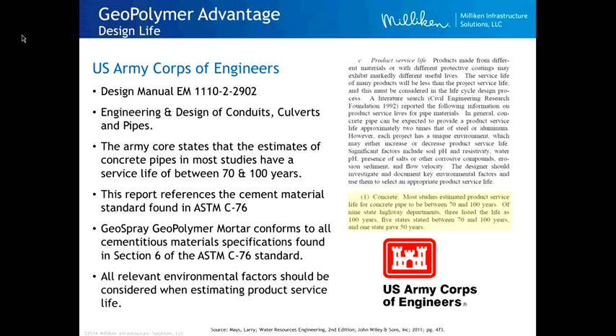And so with that material, the Corps back in the 90s did some studies on different culvert materials, and what they did is they reviewed durability studies that were out there. I know Ohio had a big durability study in the 90s. A lot of DOTs looked at materials and how they performed and what their service life would be considered. And so they did this review and found that concrete pipe has a service life between 70 and 100 years.